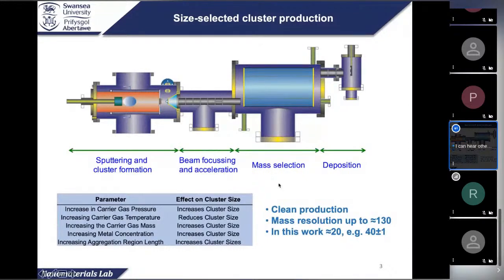So with this one, we have a mass resolution of up to about 130. That means, for example, if you produce a cluster with 130 AMU, the error bar would be ±1. But normally we just use a resolution of 20, because this will increase the current, basically the population of the cluster. If you use 130, the current will be very, very small. It takes longer to deposit.